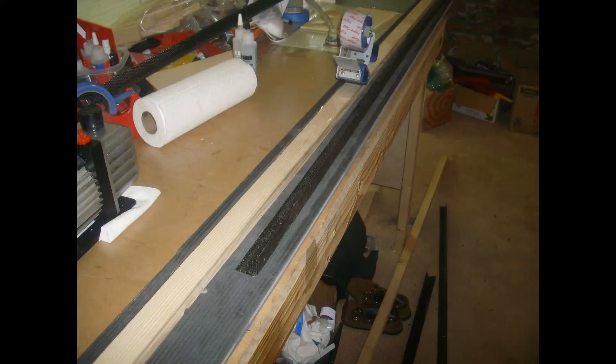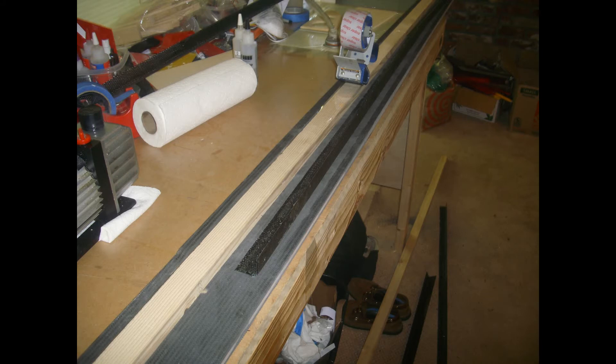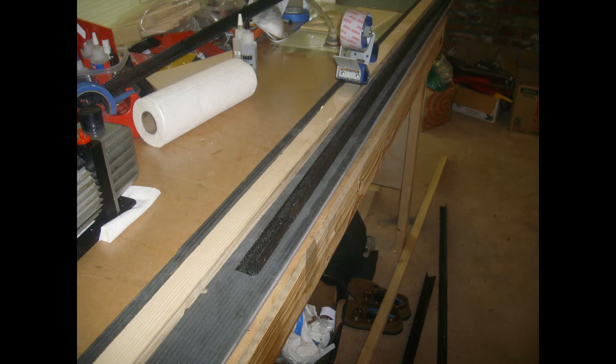In this photo, I'm showing an L-shaped flange made of one layer of 5.6-ounce carbon fiber cloth. Four of these flanges are bonded to the shear web to provide a surface for attaching the D-tube and aft wing skins. Also shown is a piece of 1x2 lumber covered with packing tape. This item is used to clamp the flange tightly to the shear web while the epoxy cures. I use T88 epoxy for this type of secondary bond. It has a shear strength of about 2,800 PSI for these types of materials. There are other epoxies that have shear strengths up to 4,500 PSI, but they are very expensive, and that level of bond strength is not needed for this type of joint.